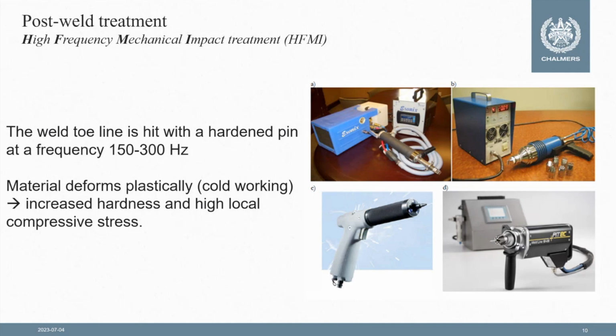The local area at the weld toe, which is the critical region where cracks initiate, is hit with a hardened pin at very high frequency, resulting in plastic deformation and cold working of this area, which has several beneficial effects on the fatigue performance of the weld toe. So it's a very local treatment method that works particularly with respect to fatigue cracking at the weld toe.